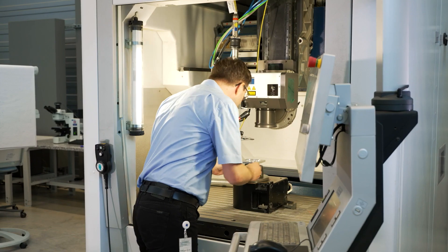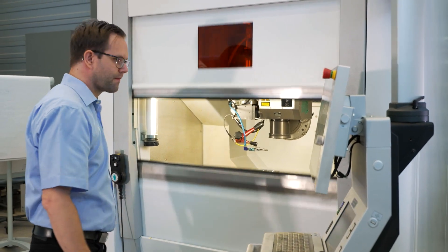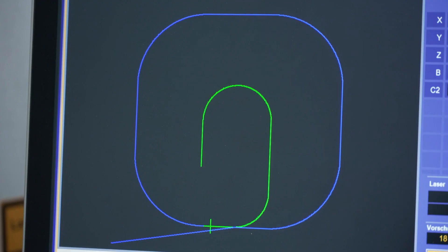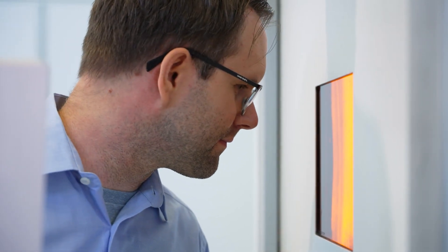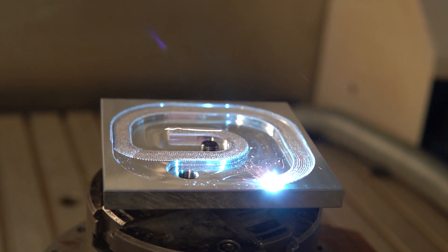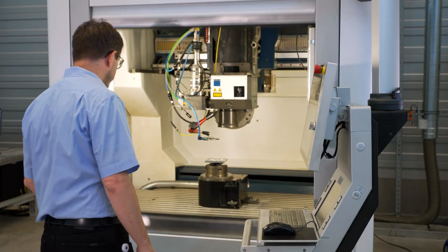For generating deep structures on large areas, laser structuring is the perfect solution. In combination with the right optics, the laser can structure any metal surface. Material is molten and subsequent laser pulses create a highly dynamic melt flow. The melt solidifies quickly and forms a structure with in-cuts — essentially, you can think of them as microhooks. The nanosecond laser TruMicro 7000 is the best choice for structuring at highest rates, thanks to its high average power of up to 2000 watts.